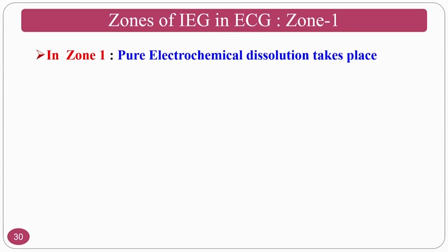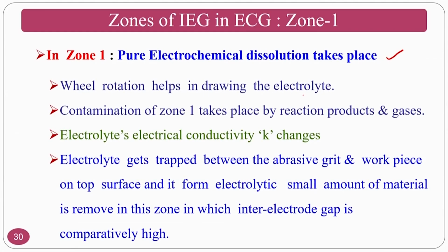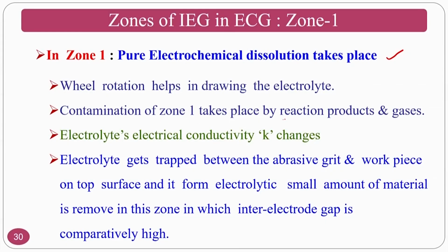Coming to stage 1 or zone 1, zone 1 is purely electrochemical dissolution. Wheel rotation helps in drawing the electrolyte. That means your wheel is rotating, because of which electrolyte will be drawn into the inter-electrode gap. Contamination of zone 1 takes place by the reaction products and gases. That means electrochemical dissolution takes place, so metal hydroxides will be forming. The electrolyte electrical conductivity K changes because you are getting metal hydroxides, so the conductivity will change. Electrolyte gets trapped between the abrasive grit and the workpiece on the top surface of it.